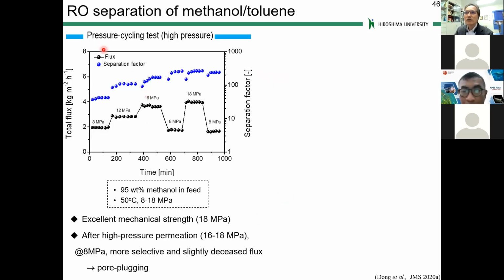Now here we have the reverse osmosis of the methanol toluene system. The experiment was started from 8 megapascal, 80 bar, and then increased to 12, 16, and then back to 8, 18, and 8 megapascal. This blue key indicates separation factors. As you can see, even after 18 megapascal, 180 bar, the membrane was stable. This membrane is actually robust at high pressure.